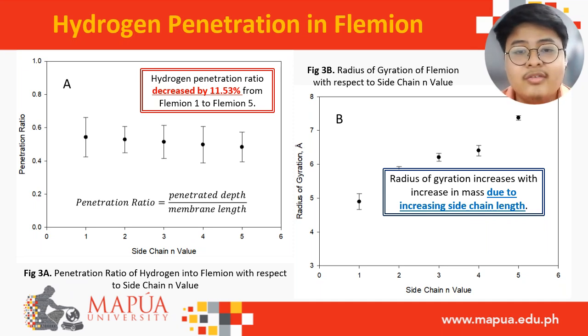This is further supported by the radius of gyration here in figure 3b, where we can see that the radius of gyration increases with increase in mass due to increasing side chain length. Now, in this context, the radius of gyration is defined as a distribution of the side chain of a polymer around its center of mass. Due to the aggregation of the hydrophobic backbones of Flemion, the side chain is able to move, which explains the higher radius of gyration for the longer side chains.